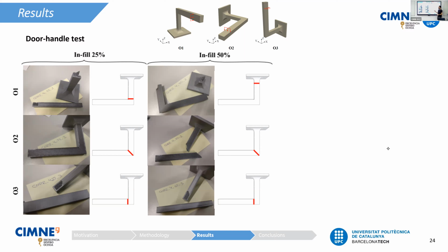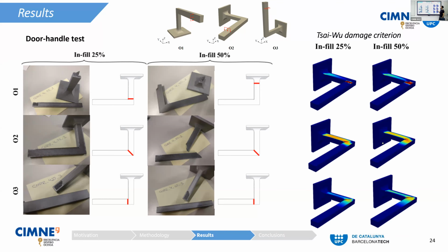Let's now compare the results with the computational results. If we use the Tsai-Wu damage criterion, we can see that the failure is always detected at the corner, meaning it fails to model this special case over here where it fails at the base. Not only that, but also in these special cases where the failure occurs vertically, this is not properly captured because it predicts that the failure occurs diagonally even in these cases.